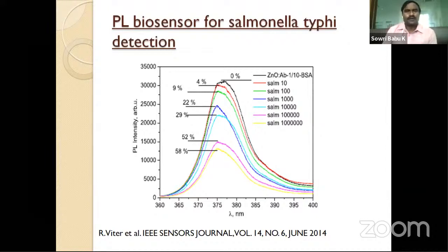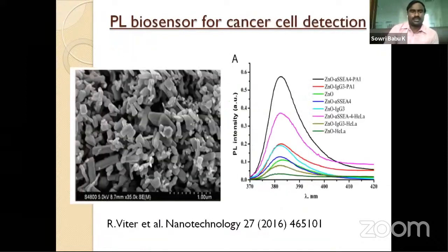They made photoluminescence biosensors in 2014 for Salmonella typhi detection, the bacterium which causes typhoid fever. If you see here, as the concentration of Salmonella typhi increases, the intensity of the emission peak decreases. So they have used the near band edge emission peak to detect the Salmonella typhi. And again, this is a picture of the nanorods made by Viter et al. They published in a Nanotechnology journal, and they used these nanoparticles to detect cancer cells. Here also you can see the emission peak intensity has changed, decreased.